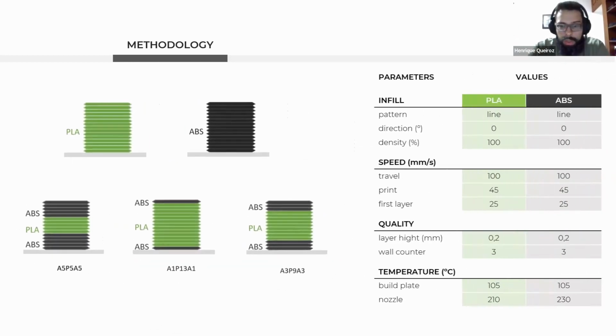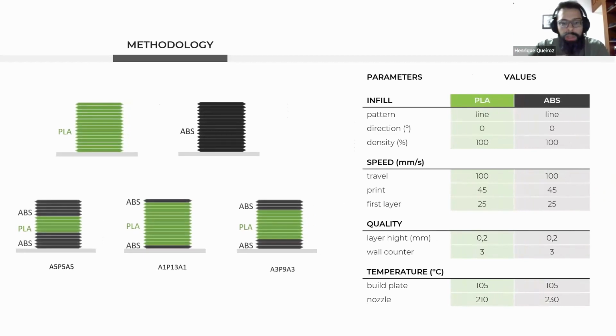And so these are the printed parameters that we used. And so we fabricated these materials, right? And so what we did was we altered the number of ABS and PLA at the same time. So we increased or decreased ABS and increased PLA. And so we tried to find an optimum point when it comes to the mechanical properties, both for tensile and flexion, and at the same time, maintain the properties as much as we can in the aging environment.